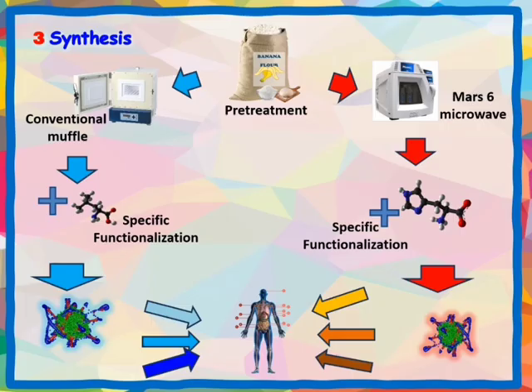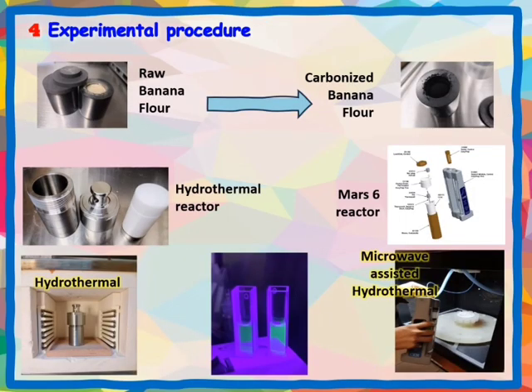In the images, we can see the banana peel flour before undergoing the carbonization process. On the right, the carbonized banana peel flour is seen. This process is a pretreatment. In the middle left, the hydrothermal reactor used is seen. It is a Teflon container hermetically sealed inside a stainless steel container. Below, the hydrothermal container inside the laboratory furnace. It should be noted that this reactor does not have holes for filling it with inert gas, so it was decided to use ambient atmosphere in both systems.